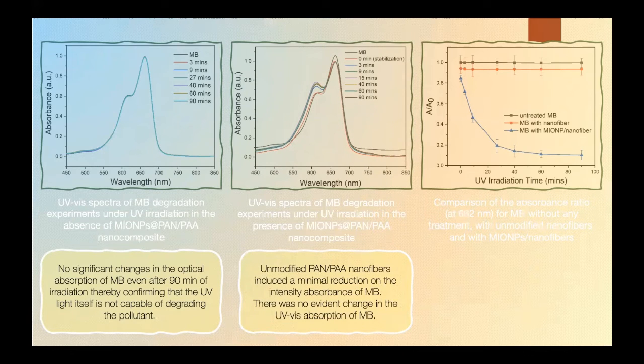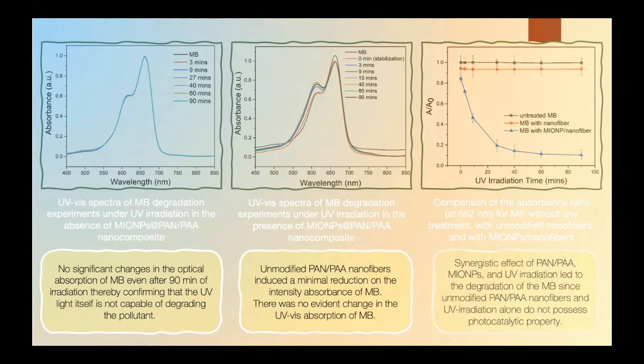We also exposed the dye solution under ultraviolet light to confirm the degradation was not induced by the energy from the UV radiation. We consequently observed no changes in the optical absorbance of the dye even after 90 minutes of irradiation, suggesting that the dye degradation was indeed due to the presence of the iron oxide.